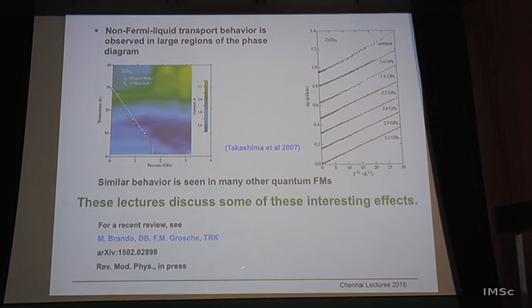And you might say, well, there's a quantum phase transition going on, so no wonder the transport looks weird. Somehow, that explanation doesn't quite cut it, because if you look at the numbers here, so here's the critical pressure, 1.6, 1.7 gigapascal something, and you see this anomalous exponent is still observed at 2 times the critical pressure. So whatever's causing it can't possibly have much to do with this quantum phase transition. It's just way too far away.